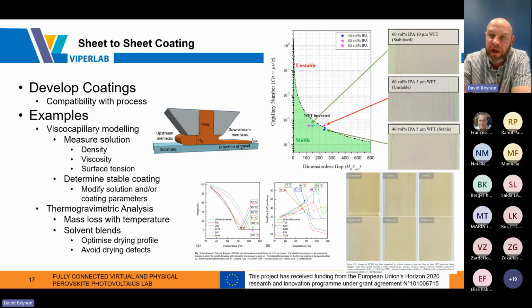And the example here is using the viscocapillary model and the stable, unstable boundary. We can modify either the solution formulation, so perhaps by altering, in this case, the amount of IPA in the solution, we'll change the surface tension and viscosity and move the coating into a stable coating window. Or we can modify the process, so we can say increase wet film thickness of our coating, which then moves it into a stable window, and we're able to coat those.